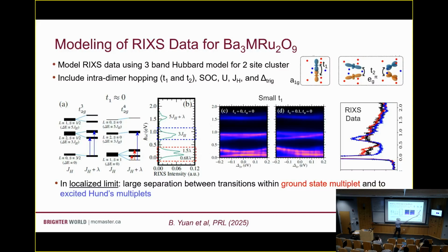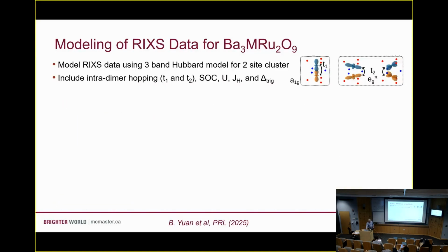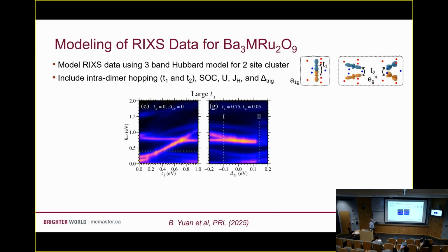Okay, so none of these looks like our lanthanum data, which is shown in the back. Okay, so the fact that this is smooth, the fact that we always get our 2 peaks below 1 eV, this is something that's inconsistent. If we turn up T1, so now instead of being 0.1, if we set it to be 0.75, or if we look at what happens if we just vary this smoothly from 0 to 1 eV, you can see that the hopping has a huge effect on where this low-lying spectral weight is.